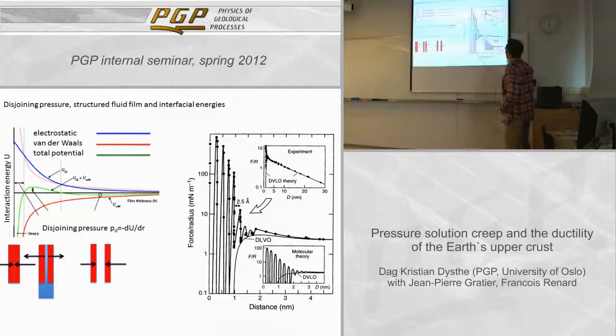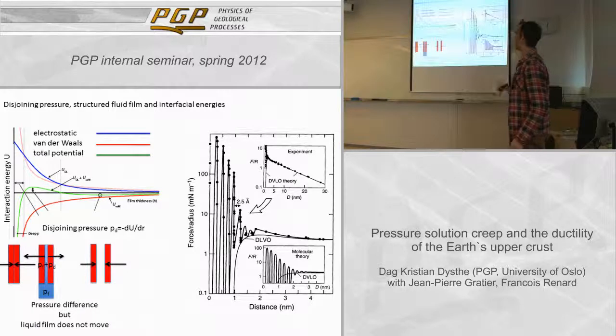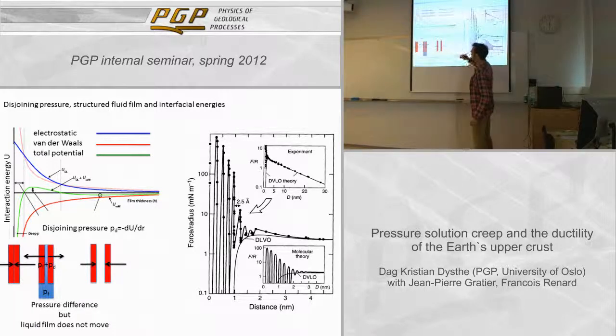And so with a very nice apparatus called the surface forces apparatus, they have measured the force as a function of distance between two surfaces, and they can actually see oscillations that are supposed to correspond to single layers of water being expelled between these surfaces as you get closer. And you can see that the net effect is that there is a large repulsion, and that you can have a thin fluid layer between two surfaces, even if there is a net force pressing them together.